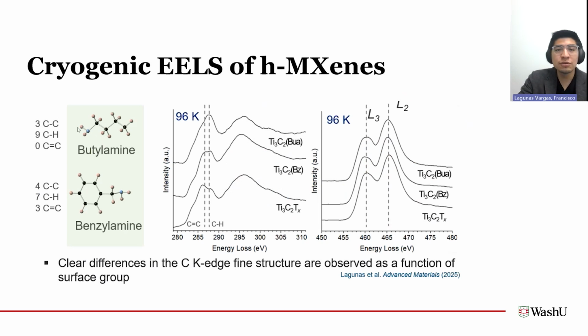So if we look at two different hybrid MXenes at cryogenic temperatures, their spacings show us that the material should be preserved at low temperatures. And we look at ones such as butylamine, which is the one with a lot of carbon-hydrogen bonds and carbon bonds, and compare it to spectra from our benzylamine terminated MXenes, which are also composed of carbon bonds and carbon-hydrogen bonds that also have carbon double bonds. Then we see this difference show up in our comparison of the carbon K edge.